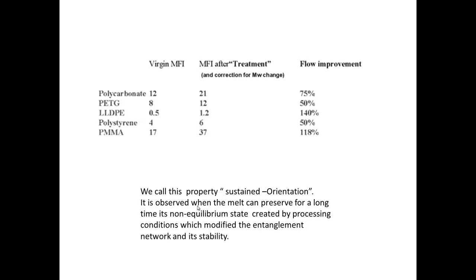And well, this was the first slide. I show that, you know, it's a factor of 3.4. So it is very sensitive to a molecular weight change, and I need to correct for this in order to determine what is coming from the process of destabilizing the entanglement network. Okay, so the sustained orientation is observed when the melt can preserve for a long time its non-equilibrium state created by processing conditions which modify the entanglement network and its stability.